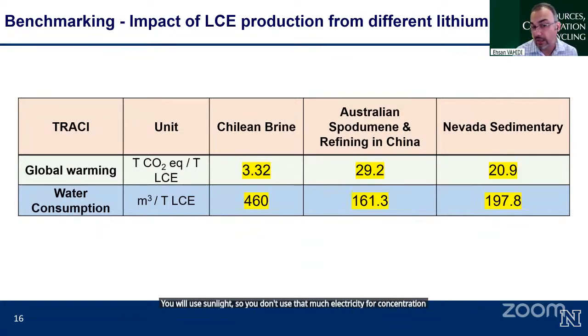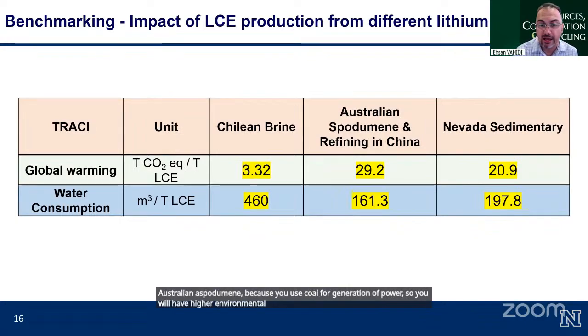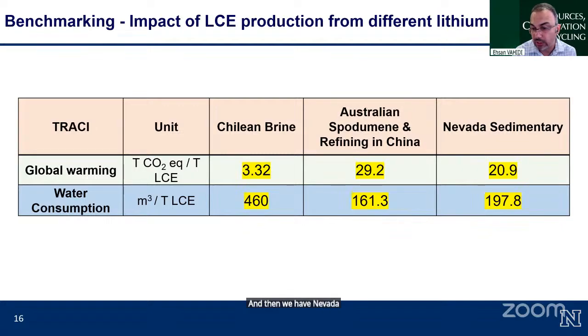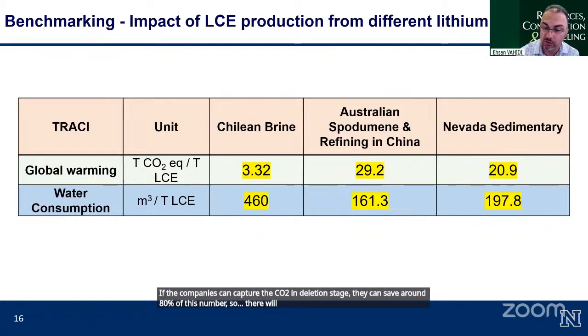At the same time, Australian spodumene, because you use coal for generation of power, will have higher environmental impact. And then we have Nevada sedimentary, almost 21 kilograms of CO2 per kilogram of lithium carbonate. And I can say that 80% of the CO2 comes from direct emission of CO2 from carbonated ore. So if the companies can capture the CO2 in the leaching stage, they can save around 80% of this number. So there will be huge potential for different companies to do carbon capture in this system.